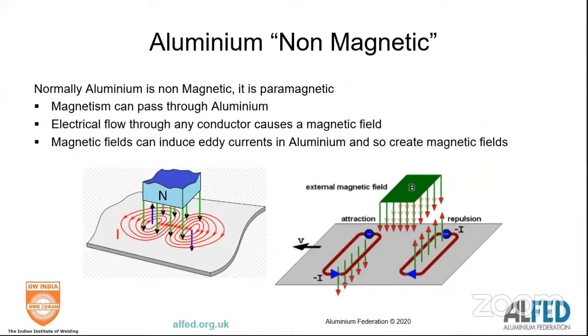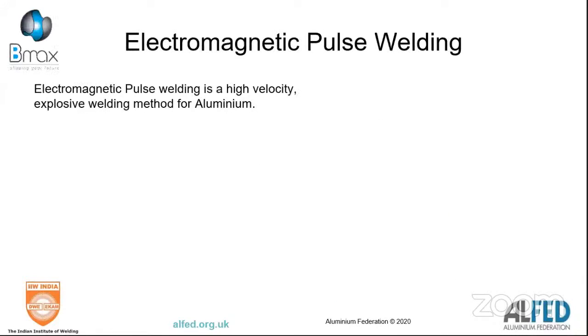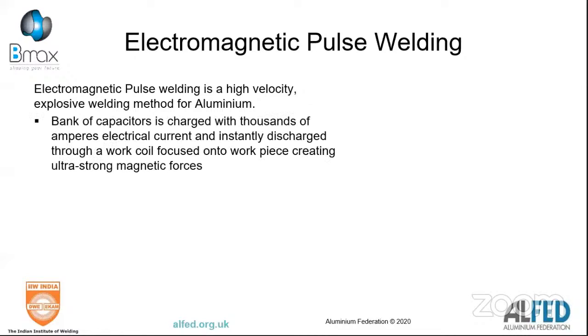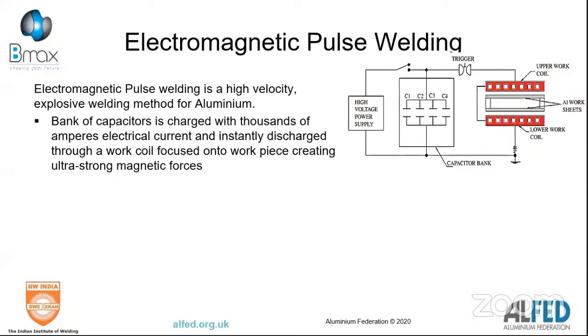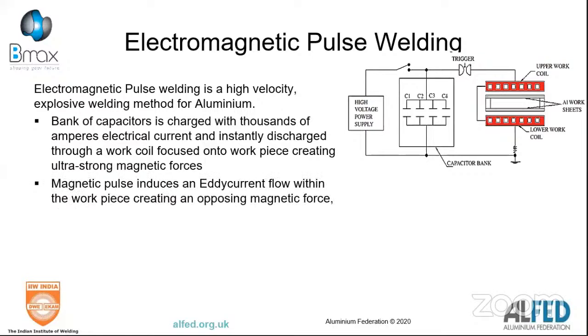Aluminium's non-magnetic. It's actually paramagnetic, which is important because it means that we can use aluminium for electromagnetic pulse welding. In electromagnetic pulse welding, you have a bank of capacitors that you charge up with very high current levels, and then you discharge instantaneously through a coil.